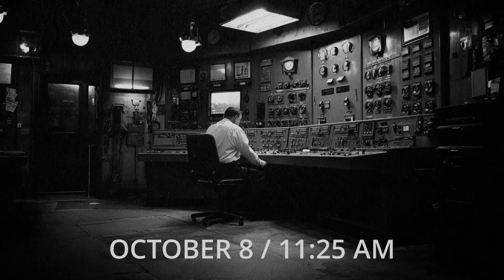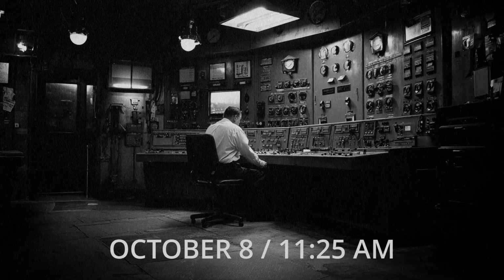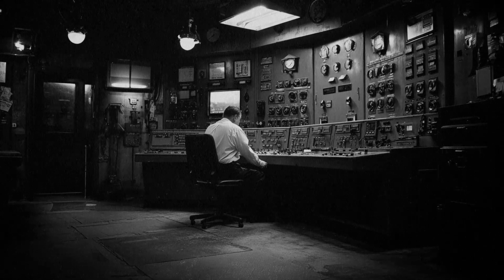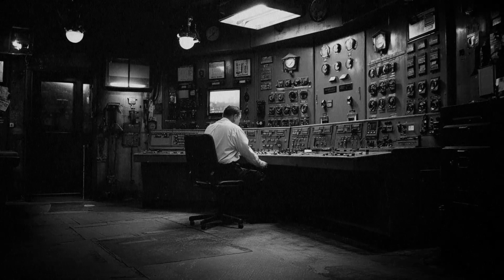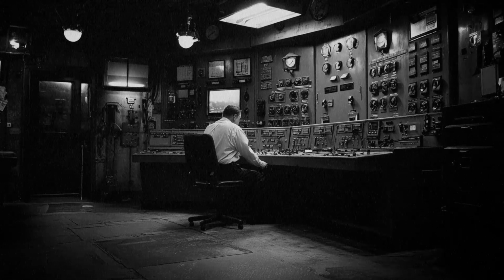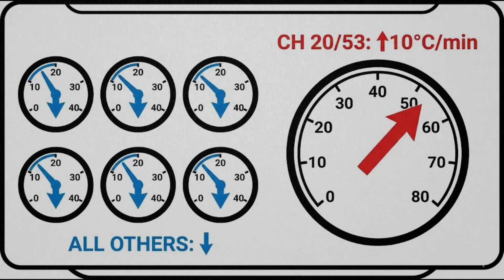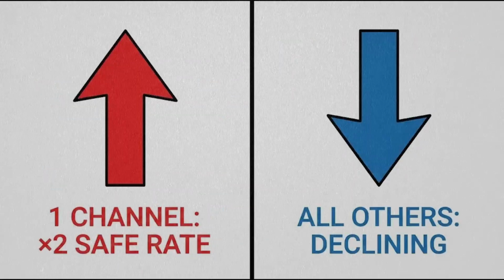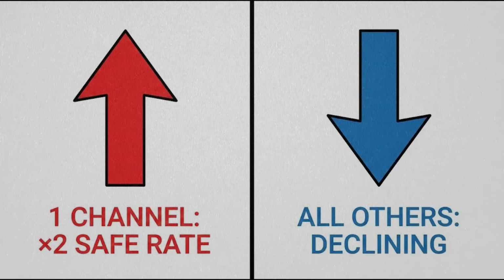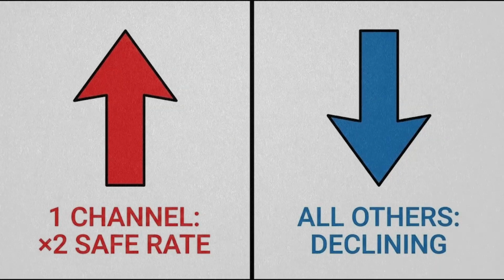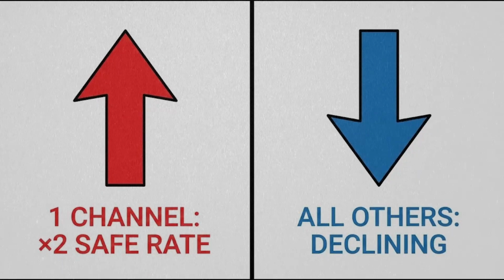On October 8th, at 11:25 in the morning, 34 hours after shutdown, one thermocouple showed something unusual. Channel 20/53 was climbing at 10 degrees Celsius per minute. The safe rate was less than 5. But on the control panel, the surrounding channels showed temperatures falling, as expected. One channel rising at twice the safe rate. Every other reading on the panel declining.